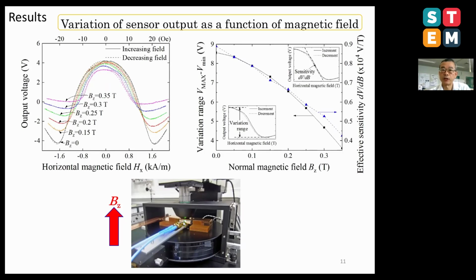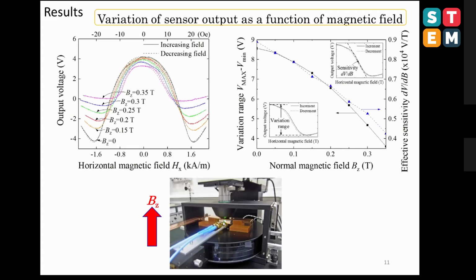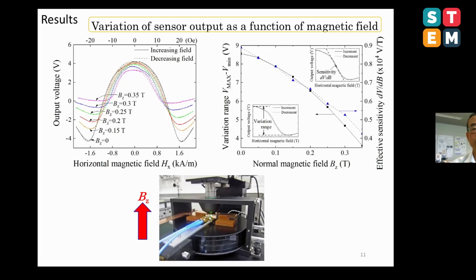The right figure shows the variation range and effective sensitivity, which are obtained from the left result. The variation range means the difference between the maximum and the minimum output value. The effective sensitivity means the maximum inclination of the sensor property. It means sensitivity. The results show that both values monotonically decrease as the normal magnetic field increases. The sensitivity at 0.35 Tesla normal field decreases by 50% relative to the one without normal field. But even if the sensitivity decreases, we can say that the sensor works in 0.35 Tesla.